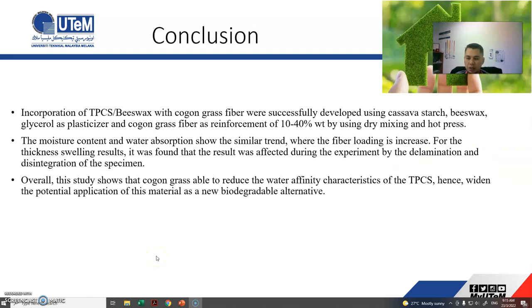As the conclusion, the incorporation of TPCS Beeswax with Cogon grass fiber was successfully developed using cassava starch, Beeswax, glycerol as the plasticizer, and Cogon grass fiber as a reinforcement at 10 to 40% by using dry mixing and hot press. The moisture content and water absorption show a similar trend, where as the fiber loading is increased, these properties decrease. For the thickness swelling, the results were affected by the delamination and disintegration of the specimens. This is what happened during the study. Overall, this study shows that Cogon grass is able to reduce the water affinity characteristics of the TPCS, hence providing potential application of the material as a new biodegradable alternative.